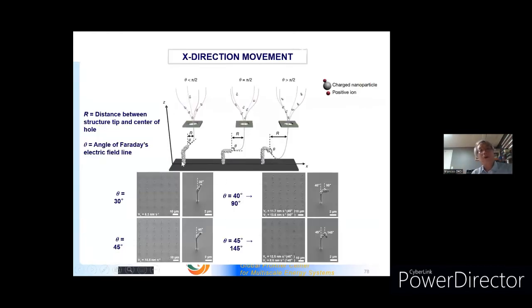Now, while you deposit nanoparticles, you can move the mask or substrate in the X direction, and then the electric field line can be changed. Then you can make a slanted structure instead of a vertical pillar. If you move this mask in this direction, you can make a 30-degree slanted structure, 45-degree, or even 90-degree, even downward growth. You see, the field is like this, and the nanoparticle should follow this field line, so downward growth could become possible.